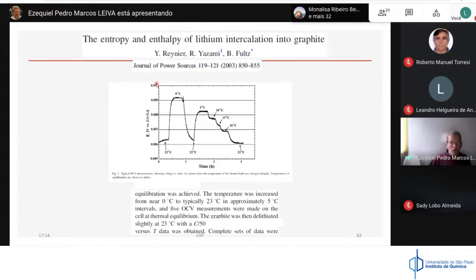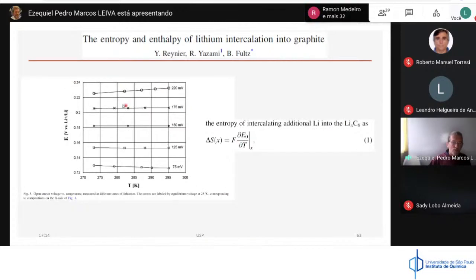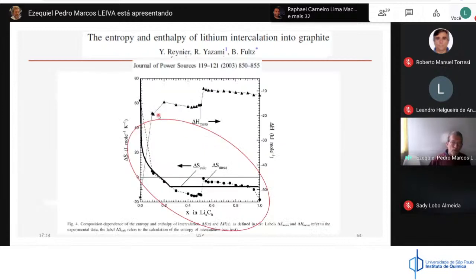You can change the temperature. From the change of the temperature of the system, you get different equilibrium potentials. If you plot the equilibrium potential as a function of the temperature and you take the derivative, you can get the partial molar entropy. And when you plot the partial molar entropy as a function of the configuration of the system, you find this behavior. You see the partial molar entropy coming down, you see a step at about one half of the filling of the structure, and later you see again a decrease.